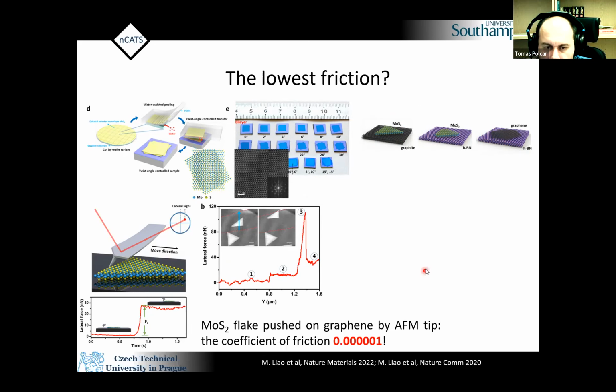So what we did was divide friction into 2 parts. One we call area, which depends on area, and the other is edge, which depends on perimeter, which is this size. And what you can see here, when we look at the shear strength of molybdenum disulfide, is that it goes down with the flake area, and then the edge pinning strength is almost the same regardless of how big the domain is. So basically, what we find here is that for molybdenum disulfide, the edge pinning effect, which is actually negative here, is very strong.